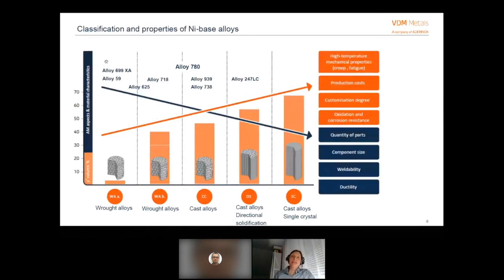And you can see here some examples of alloys which are used, or typical alloys for this application. Alloy 59 is the next generation of C alloys. It shows really strongly improved corrosion resistance in comparison to C276. Alloy 699XA was developed for application at high temperature corrosion called metal dusting.